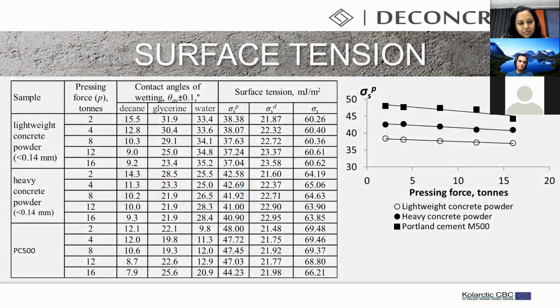Then we study the surface tension, and I will explain why. The destruction of concrete during crushing occurs mainly along the cement stone or along the surface of its contact with a large aggregate. Consequently, when using crushed stone from recycled concrete in concrete mixes, the strength of the new concrete will largely be determined by the adhesion of new cement stone to the old one. The above also applies to concrete powder.